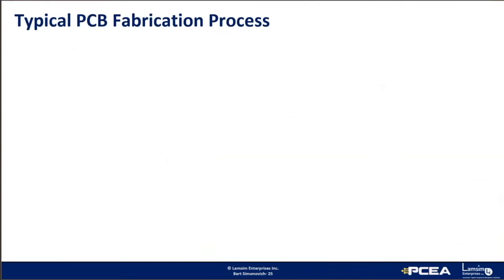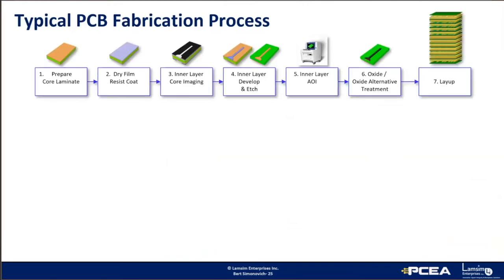So the typical multi-layer PCB fabrication process is quite a complicated affair. It begins with a double-sided copper core laminate, then goes through a series of steps where the PCB artwork patterns are imaged onto each side of the core layers. Then unwanted copper is etched away, leaving the final artwork patterns. All the cores are then prepared and assembled into a layup, and everything will be glued together with prepreg sheets.